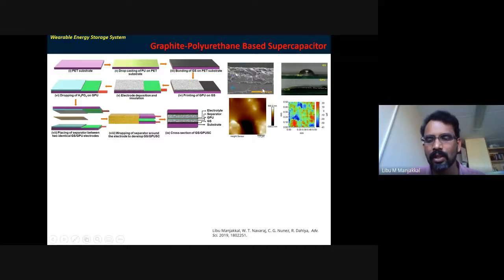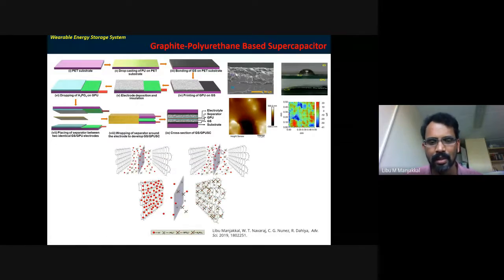The major advantage of this material is that you can see clearly here, there is a bubble on the top of it. When you use only a graphene sheet in a normal device, it looks like a bubble when you drop the electrolyte. But when I used my new composite material, the electrolyte is fully distributed and it has a very good surface area for the electrochemical reaction. And again it is a graphene based material, the graphene polyurethane composite I used.